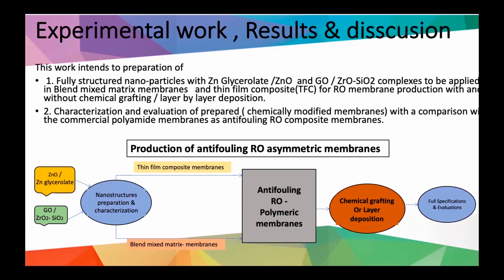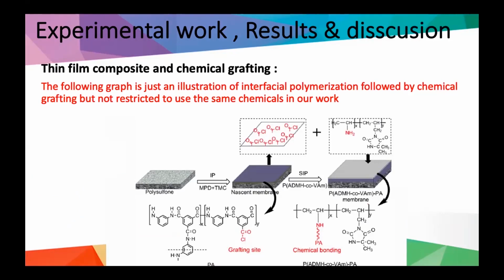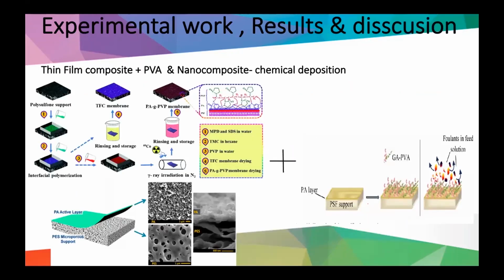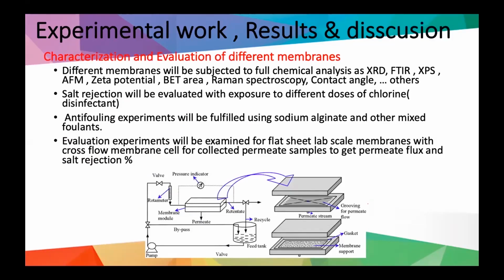Here you can find some illustrations of the chemical bonding, for example the chemical grafting, which is done over the thin film composite, and how the use of chemical grafting and some cross-linking over the membrane surface will greatly enhance its applicability in terms of flux and salt rejection. Also, the presence of polyvinyl alcohol and how to benefit from this polymer is illustrated here. The different structure, as you can see in this diagram, shows the grooves for the permeate flow. The assembly of the testing structure for the membrane will play an important role in measuring the performance of the membrane, and also in the fouling experiments.